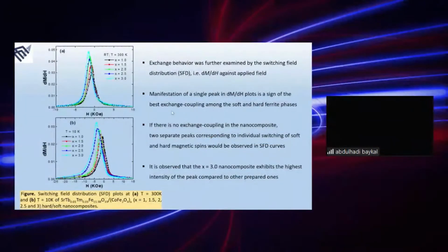This is another important parameter for us. Why? Because we are arguing that we have exchange coupling in our samples, and the indication of the presence of exchange coupling in all our 5 products can be proved by the presence of a single peak here. For all of them we have a single peak. In the figures A and B, A is for room temperature and B is for 10 Kelvin. If the number of peaks were more than 1, let's say 2, this would show the absence of exchange coupling.